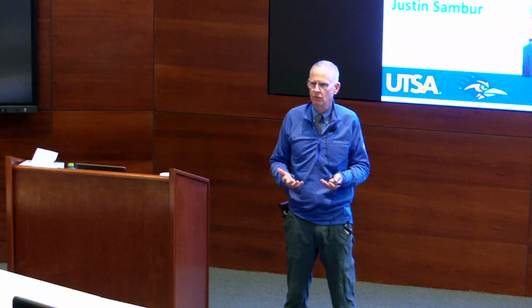It turns out we have done quite a lot of that. The first work that we did, and we've done over the years, is what's called layer by layer deposition. What I mean by that is if you have a polyelectrolyte in solution and a surface, you dip the surface in, and the polyelectrolyte adsorbs to the surface, monolayer coverage. Then if you take that surface out and dip it into a solution of an oppositely charged polyelectrolyte, you coat it again. Then you can go back and forth and build up multilayer structures, basically about one layer at a time. So you can make a 10-layer structure that's about 10 nanometers in thickness. If you're really patient and have a robot, you can make a 50-layer structure, which is about 50 nanometers. So we've done that kind of work.